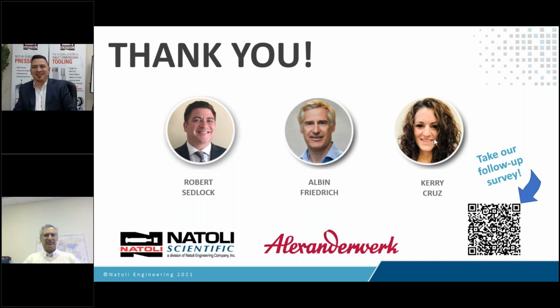All right, Al, the first question for you is, what is the rationale for a gap setting of 1.5 millimeters? We selected a 1.5 millimeter gap during our studies because we were trying to match the last screen size that we used in RFG number 2. So sometimes I try and match gap size versus top particle size that you're looking for in your particle size distribution of the final granule that we're getting. So that was the logic in that one. The gap is variable. You can pretty much pick anything you want, but matching the gap to the top screen size minimizes fines.